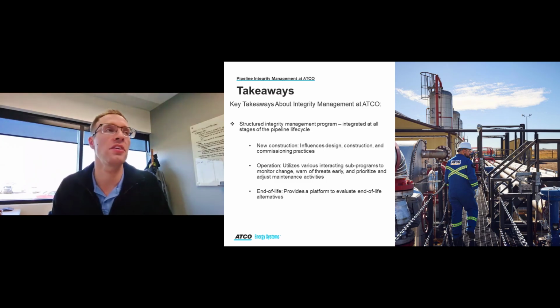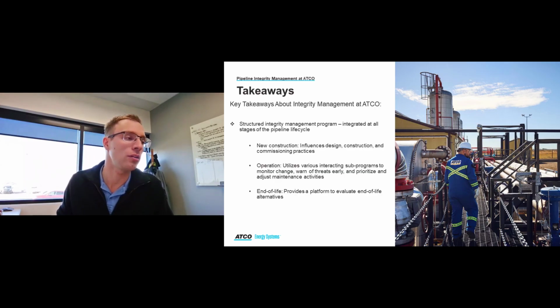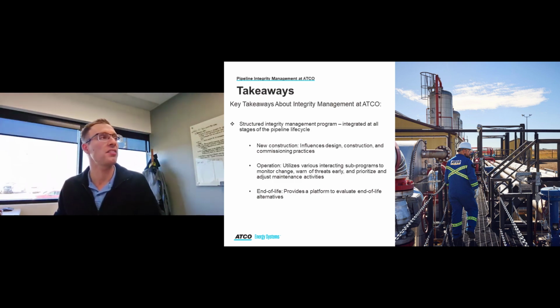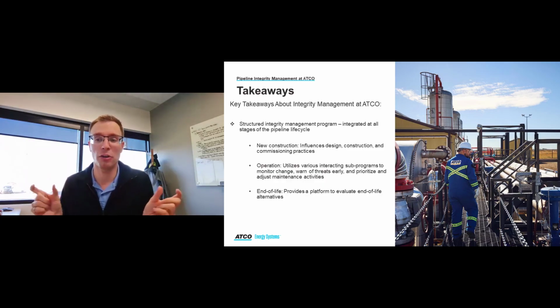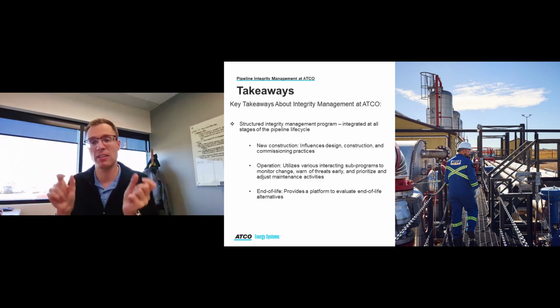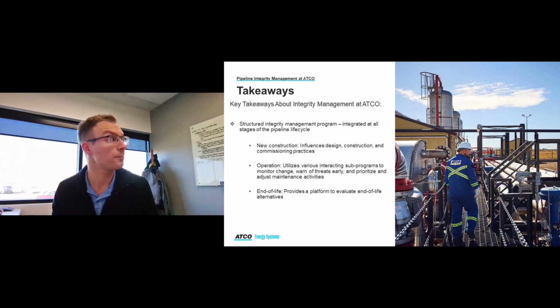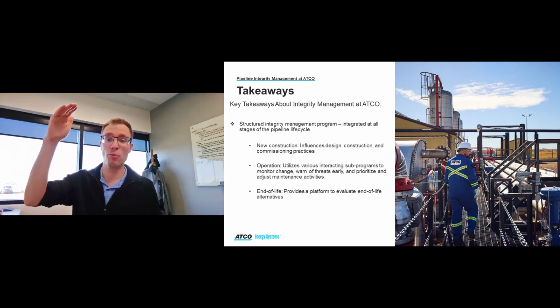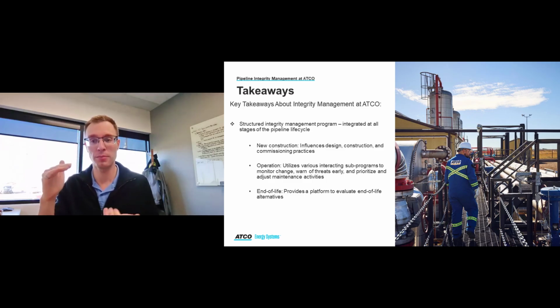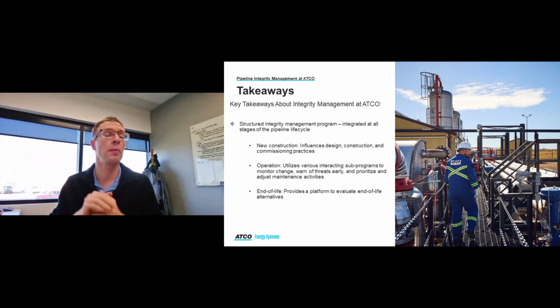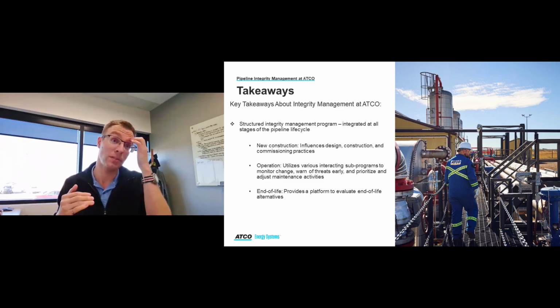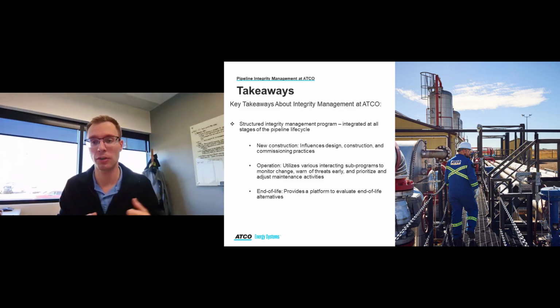Other examples of design considerations that maybe have the largest impact have a lot to do with the physical attributes of the pipe itself. So again, if we're just talking about steel, one of the biggest things that we can do to make steel pipe more resilient to integrity threats is to just make it thicker walled. So in other words, have more wall of that steel pipe, more physical material to work with. And the way that I see it is that benefits us in two ways. One, from a corrosion perspective, it means there's just more material that corrosion has to get through before it becomes a concern. And two, depending on the diameter of the pipe, it can actually reduce the pipe's susceptibility to deformation, things like denting, for example.